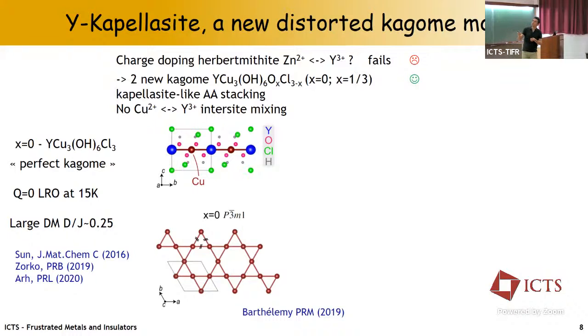For both compounds, since yttrium and copper are very different ions, you don't expect, and we don't get, intersite mixing on the two sides. So the copper layer should be rather perfect. And so this material is a perfect Kagome lattice, and it freezes at 15 K to long-range order in a Q equals 0 structure that was understood as a result of a large Dzyaloshinskii-Moriya interaction below the critical value that stabilized long-range order.